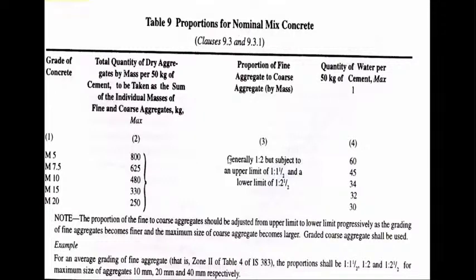Okay, coming to the note below, it's the proportion of the fine to coarse aggregate, which is the 1:2 or 1:1.5 or 1:2.5, as described in column number 3. The proportion of the fine to coarse aggregate should be adjusted from upper limit to lower limit, which is the upper limit 1:1.5, which is the lower limit 1:2.5. It should be adjusted from upper limit to lower limit progressively as the grading of fine aggregates becomes finer, which means the finer it becomes, you should go lower.